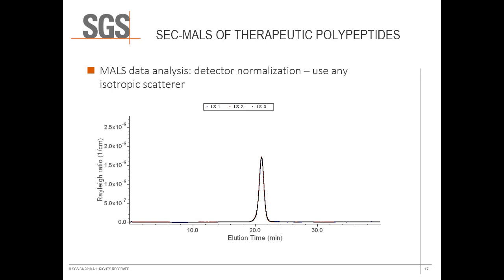These corrections are easily achieved with the single well-selected polymer standard. This standard is also well suited for system suitability evaluation. Run at the beginning and the end of the analysis batch, retention time and peak area reproducibility can be evaluated, as well as the accuracy of absolute molar mass calculations when compared with the supplier's certificate of analysis.